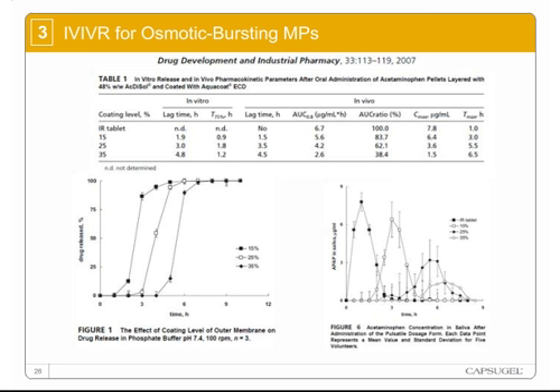A hallmark of the classic osmotic push-pull osmotic pump monolithic tablets is their strong in vitro and in vivo relationships that come from the mechanism of release relying only on water activity outside of the tablets. When an osmotic bursting multiparticulate is well designed and formulated, these particles can also achieve a very strong in vitro and in vivo relationship. Shown in this literature example is the in vitro and in vivo relationship for in vitro release, the lag followed by the very pulsatile release, again, similar to the case study that I showed, just dependent on the barrier coating thickness, and then the in vivo concentrations that were achieved based on those different particles and their lag times that were generated by formulation.